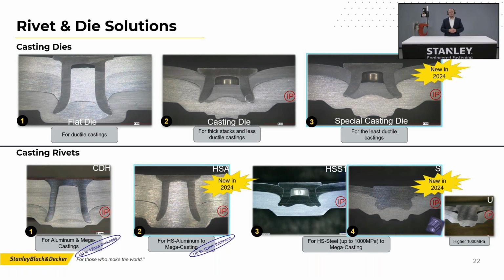And then when the joining partner gets more challenging, meaning a harder steel, high strength steel, we have the HSS rivet, and brand new, the S rivet for joining HSS steels or even higher, up to 1000 megapascal in 1.6 millimeter thickness, with these rivets into F-temper mega castings. ALSI 10, ALSI 7, all of those work. And if you go even harder, like even harder steel, you need to go to the U-rivet, and we also have some success there, but it's depending on the material thickness of the steel.